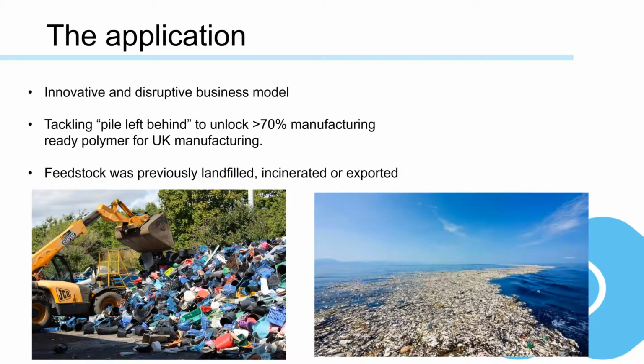When we developed BOSS, it was originally developed to look at the problem stream of caps and bottle caps from PET recycling plants. For PET recycling, bottles are individually selected, removed from the pile that you see in the bottom left of the screen, and then sent to be granulated, washed, and the PET is recovered. But you end up with the bottle caps and ring enclosure as a problem stream. The stream is a mix of PE, PP, and residual PET, and that's what we designed our BOSS for.